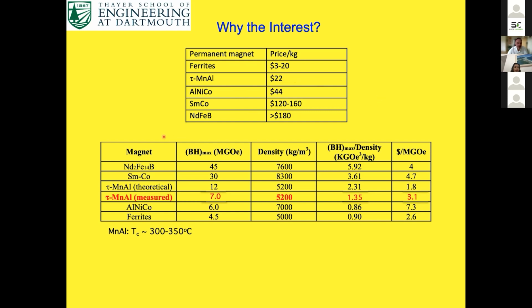but that's just a guess, really. But if we look at the properties of magnets, when you're looking at a permanent magnet, the parameter of interest is BH max, the energy product. And again, there's a range. So the worst magnets, the ferrites, have a value in this parameter in MGOe of 4.5. And at the other end of the scale, there's neodymium iron boron, which has an energy product 10 times greater than that of ferrites. And there's a sort of gap in between here. And this is where tau manganese aluminum could sit. So theoretically, it has a potential value of 12, but the best anybody's done so far is actually